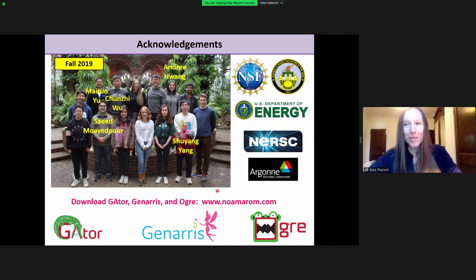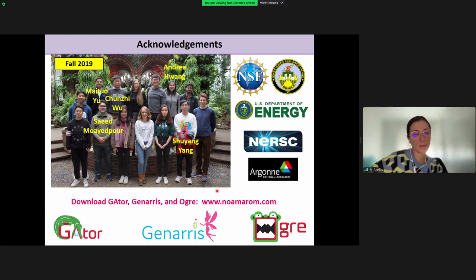Just one more thing about the interface configurations. I think that for getting the right interface distance and registry, especially the interface distance, the van der Waals correction is probably more important than the DFT plus U. We do use the van der Waals correction in our interface simulations, but then the U is critical for the electronic properties.